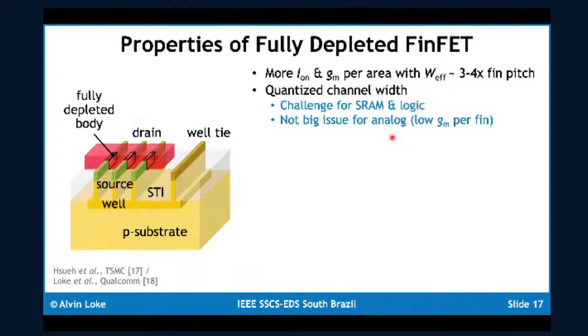Some properties of the fully depleted fin: one key advantage of going into the third dimension is that the device width per fin, which is basically twice the height of the fin plus one width of the fin, is quite substantial compared to the fin pitch. In fact, the effective width is about 3 to 4 times the fin pitch, which means you're getting a lot more on current and therefore more GM per unit area.